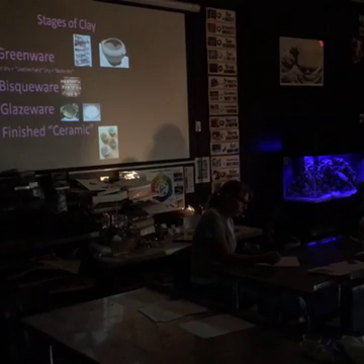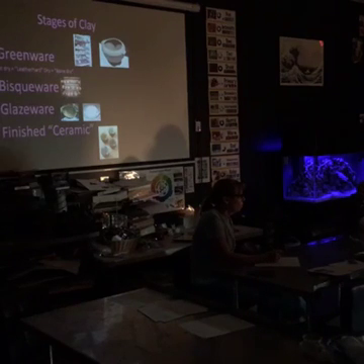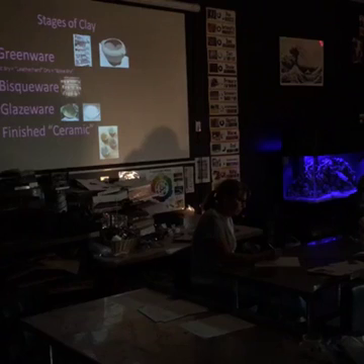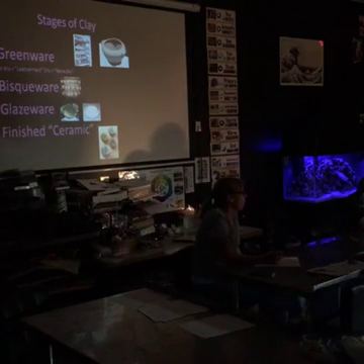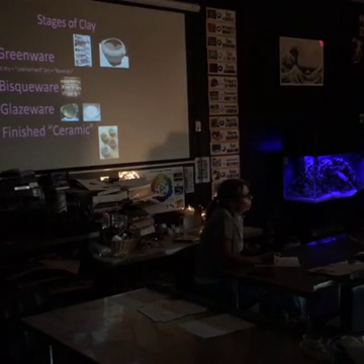So that shrinkage is important not only for planning, but also so that you understand why you can't have any water or air. I already mentioned water is a no-no, you just gotta let it dry to avoid that. Air bubbles or air pockets: you see how this has a hole in it? If this hole wasn't in it and this was an air pocket, this would violently explode because of the shrinkage compacting that trapped air.